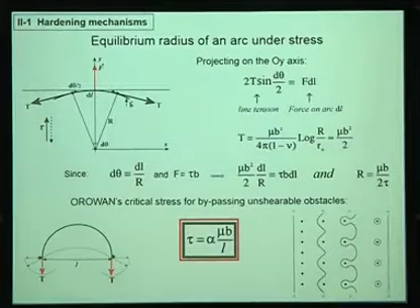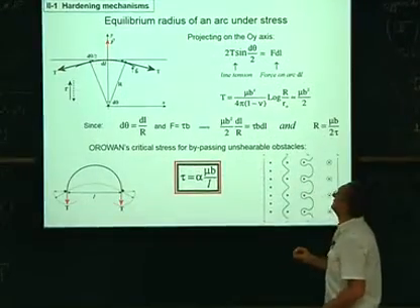For that, if we go to the scale of dislocations, there is one tool which is very important, and I think the experimentalists use that tool many times also to analyze their pictures. It is what we call the line tension analysis. Line tension analysis means if you take a piece of dislocation, the black curve here, just imagine that it is a curved dislocation. And you compute the line tension, so you have some line energy, T. T is typically due to the energy of the line, mu b squared over 2 pi (1 minus nu). This is the line energy.